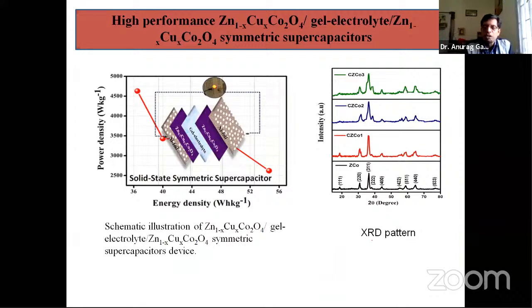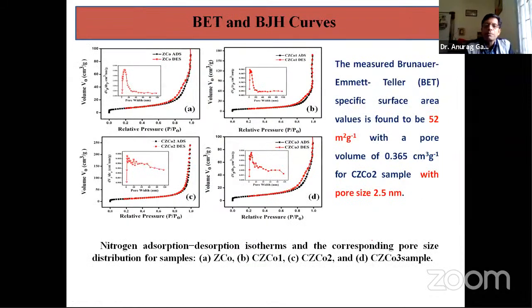For the solid state symmetric supercapacitors, we use nickel foil, and again the zinc cobalt oxide on nickel foil. It's a symmetric device again using gel electrolytes. So this zinc cobalt copper oxide gel electrolyte symmetric supercapacitor is being fabricated, and you could see the BET measurement.